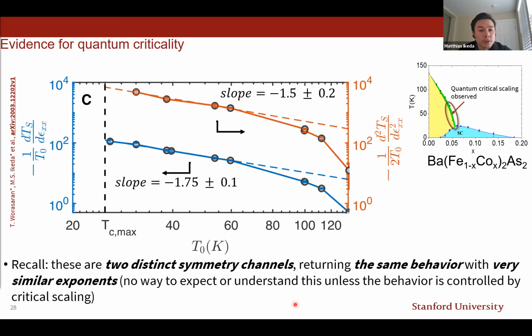It gets even more interesting when comparing the slopes of these linear functions here. And the slopes are extremely similar. They are actually the same within the experimental error bars. And this is a result that can only be understood if these two strain components, the symmetry conserving, but also the symmetry breaking strain, tune the system further away or closer to a single quantum critical point.